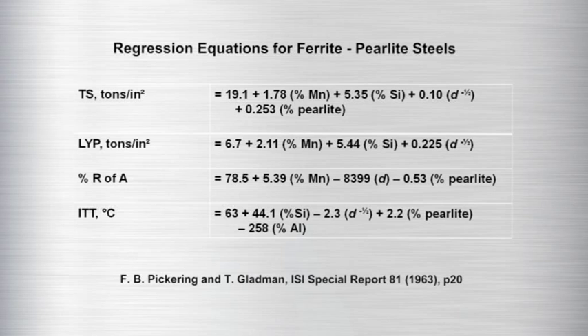The regression analysis work that I've talked about relied extensively on work that had previously been carried out by Hall and Petch to show the effect of grain size on yield strength, and by Ashby and Orowan, who had shown the effects of precipitate particles on yield strength. These formats were used in the regression work and proved very successful in predicting the results, the mechanical properties particularly, yield strength and toughness.